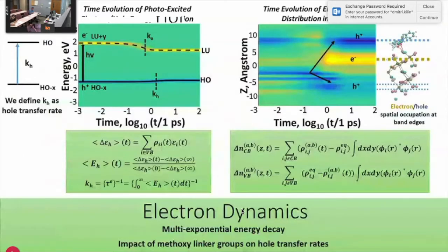So, onto our electron dynamics. We compute our electron dynamics using the density matrix formalism and solving the Redfield equations, which we break apart into the Liouville superoperator and the Redfield superoperator. The Redfield operator provides energy dissipation due to electron-phonon interactions. And for each time step, we solve those equations, and they give energy occupations for each state.